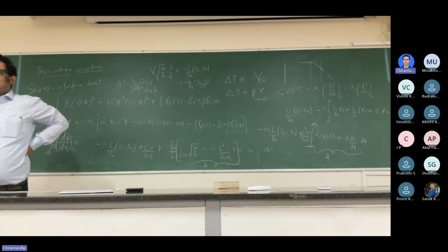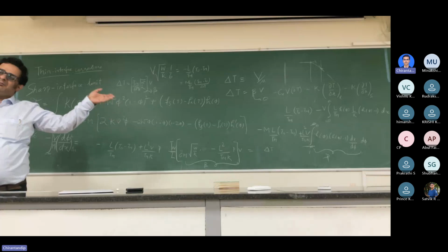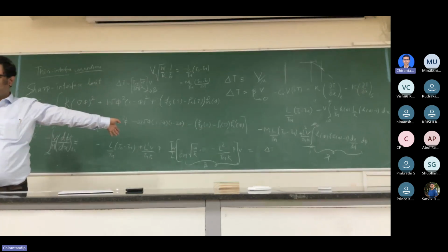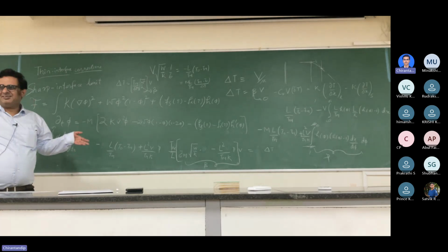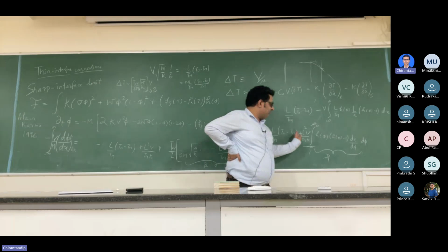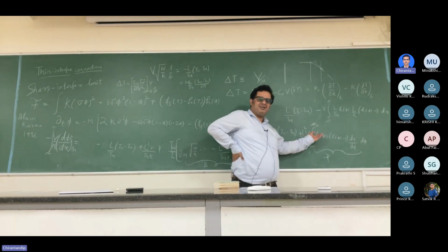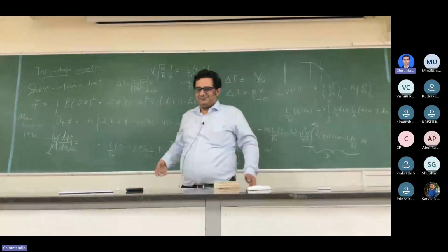That is not a clean derivation. I mean, you could do it, but it's essentially going to involve the same sort of integrals, if I imagine it correctly. Because you are going to basically find out the average driving force across the interface and then impose that. But that is effectively what you are doing anyway. Actually, Peter Voorhees has done one. Yeah, but that's the same thing, because what you are going to be assuming is that this effective driving force has to be such that you compute the driving force and effectively replace it with the average driving force across the interface. That's it.